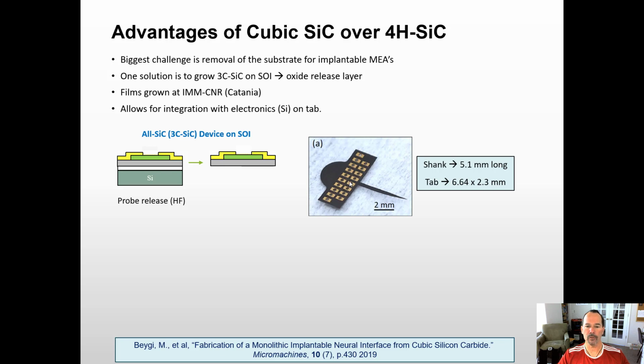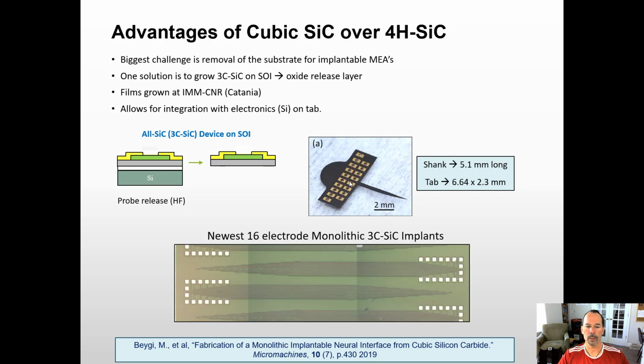And again, this is the device photo I showed you before. For our next generation, we had a problem with packaging. We've now gone to the same footprint that NeuroNexus uses, and we're partnering with them to package our devices. Here we see the pre-probe definition, etch, and release state. These devices are actually being run through our DRIE tool this week. And once we do that, we'll flip, thin the silicon off the substrate, and release with HF. So we're looking forward to seeing how these implants work.